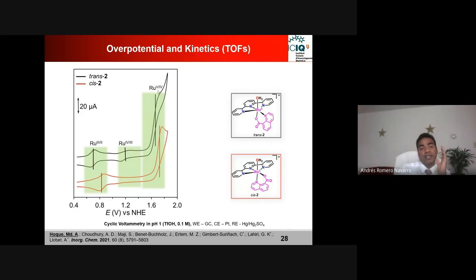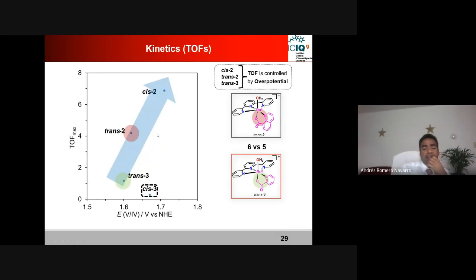So for example, the trans one is showing approximately 100 millivolt lower overpotential as compared to the cis isomer. So you can see that by changing this geometry, just the geometric position, you can lower the overpotential. And then we also calculate the turnover frequency because we wanted to know which one is working faster.